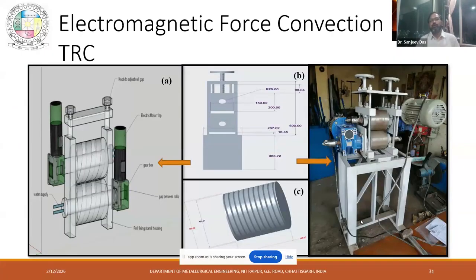Now we have to see whether this really works on a real industrial scale, or in some prototype. So we made a twin roll caster. What is a twin roll caster? We have two rolls rolling in opposite directions. You put the liquid metal from one side and you get the solid strip. You can make near net shape strips, so you can certainly decrease a lot of hot rolling and cold rolling, and really save a lot of running cost and capital investment.